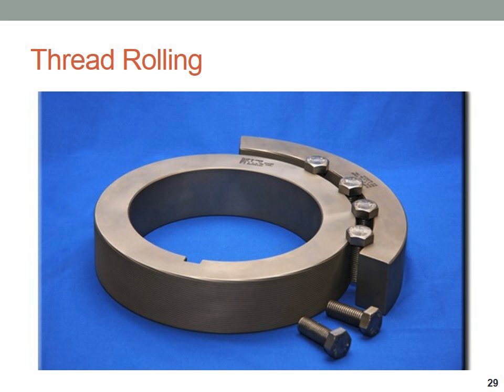Threads are formed in two ways, typically thread cutting and thread rolling. Thread cutting is sort of self-explanatory. That's typically done with a chaser or almost a lathe type of setup. Thread rolling is actually done with two dies that have the profile of the threads included. And basically what they do is, under very high pressure, roll the threads into the bolt, so there's no cutting. There are some advantages to thread rolling. There's a little bit better strength because of the cold working, and the grain flow is maintained rather than cut away.